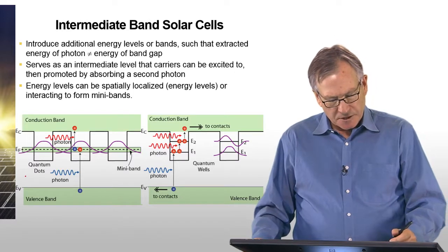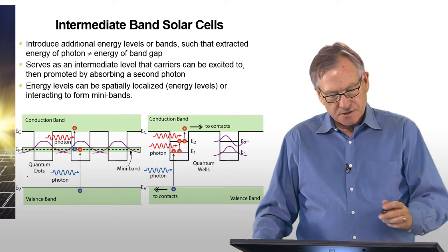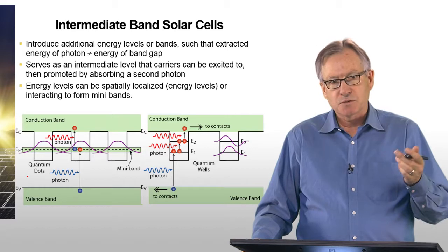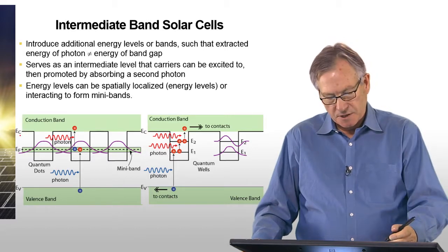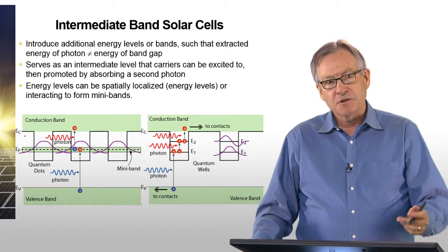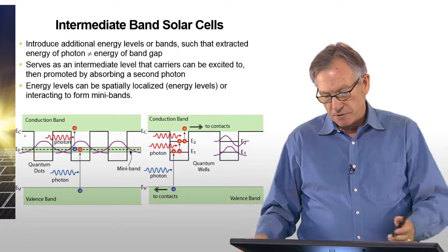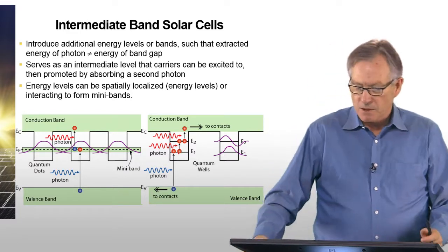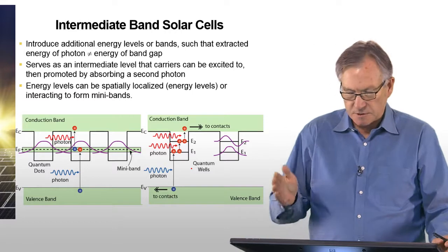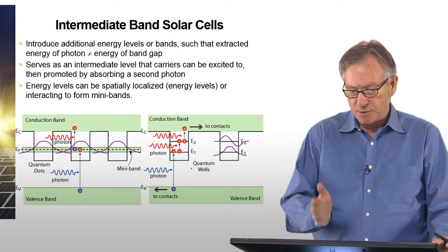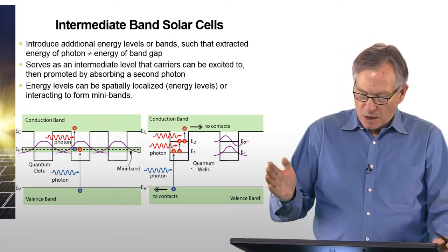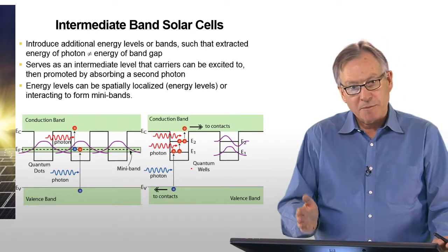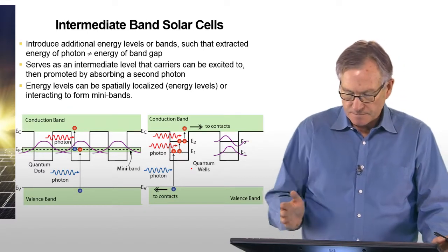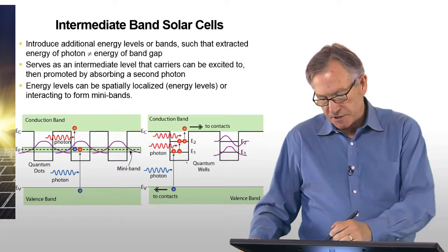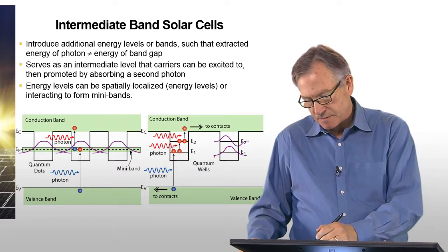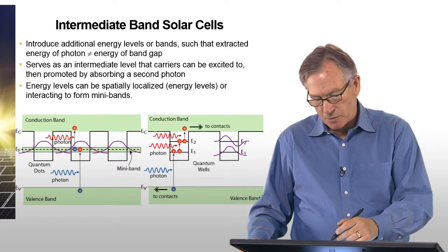And what's shown schematically down below are the energetics of two realizations of this, one involving quantum dots embedded into a matrix of a host material, and another, quantum wells. The one on the right can be grown, as I mentioned, by epitaxial growth, where you grow wide bandgap material and then grow narrow bandgap material and grow wide bandgap material again. And that introduces narrow gaps or narrow levels inside of a material with a larger bandgap.